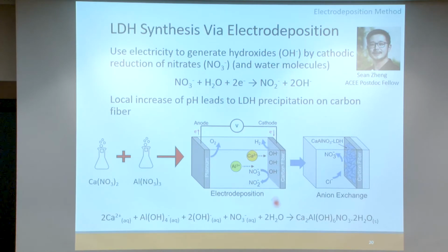And so this increases the local pH around this electrode, this carbon fiber, such that LDH precipitates on top of the carbon fiber. And so the chemical equation is written down here in terms of calcium, and now we're looking at aluminium, and once again there's a tetrahydroxide species that gets incorporated to create your layered double hydroxide. So that's how you can actually directly deposit the layered double hydroxide onto a thin piece of material.